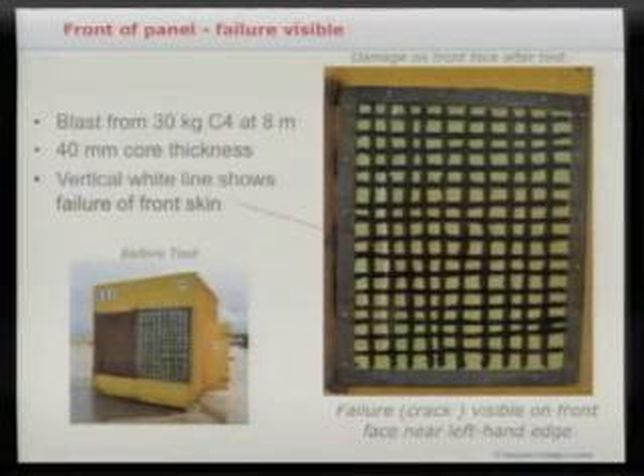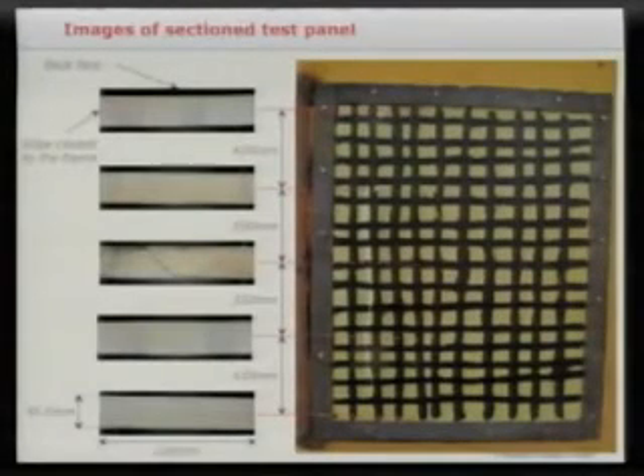What's happening here is that the initiation process is starting in the corner where the panel is built in and constrained, but in the center of the panel it's deflecting. And in that transition zone is where the cracking initiates. And when you section this, in fact, we're doing some work with Southampton where we're putting all this into an X-ray tomography machine and getting a 3D section. But here, this is what we've done here, is just a section through the sample.